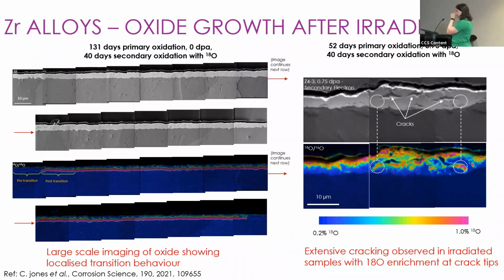The other image here is after 0.75 displacements per atom. You can see now the oxide is looking a bit of a mess. We've got a lot of cracking along the middle here. And we can also, again, look at pathways by which oxygen-18 is penetrating down through our oxide. So you can see we've got these large cracks just here. And on these crack tips, we can see oxygen-18 is able to penetrate from the water out here through these cracks, and it's growing new oxide and heading off towards the metal oxide interface. So we can look at pathways. You can see another pathway probably starting to form here, of this oxygen-18 penetrating through this protective oxide down to the metal oxide interface.